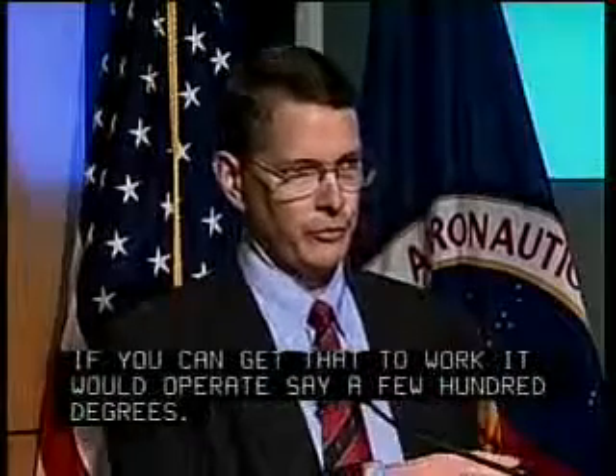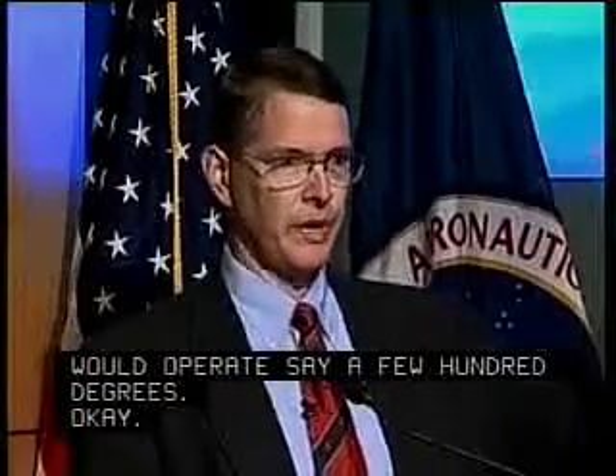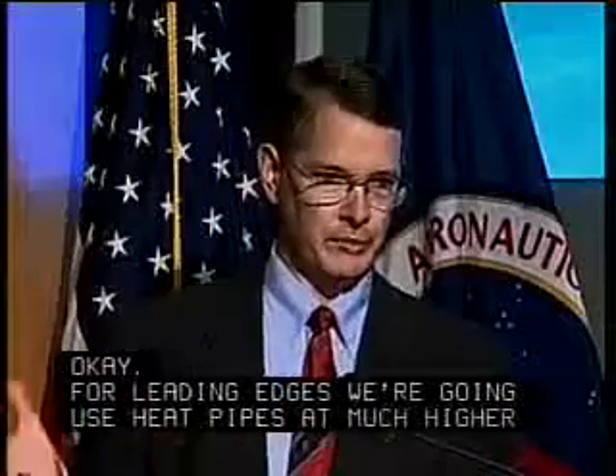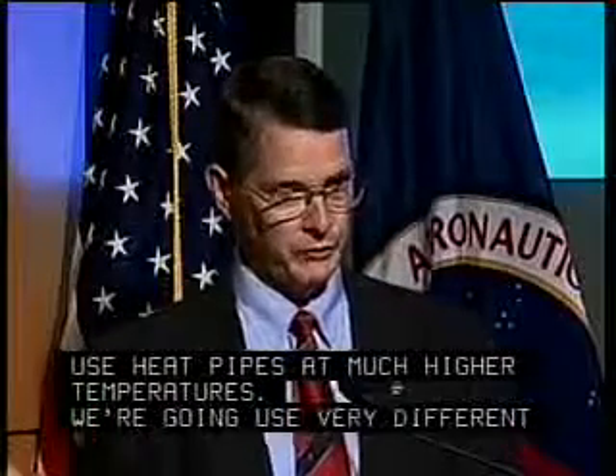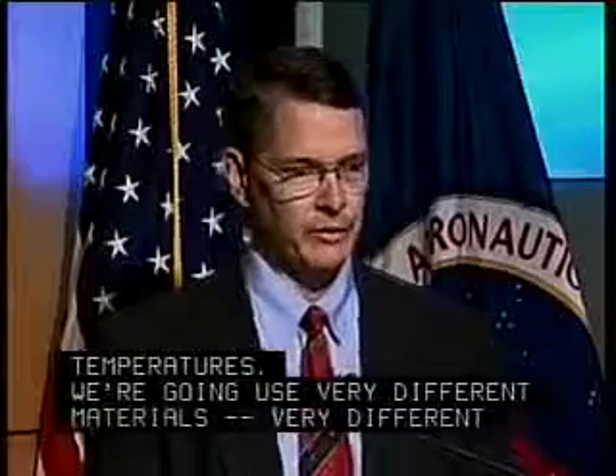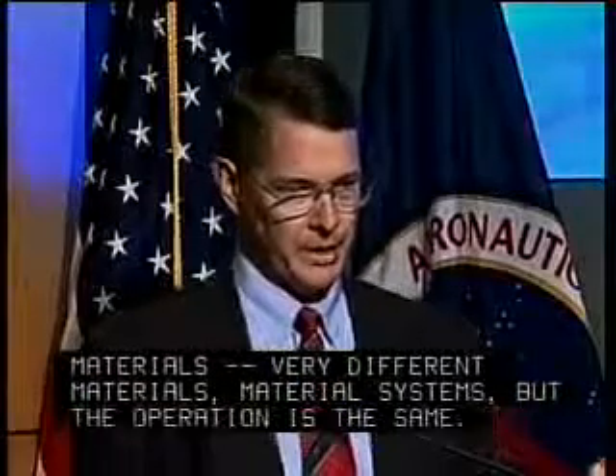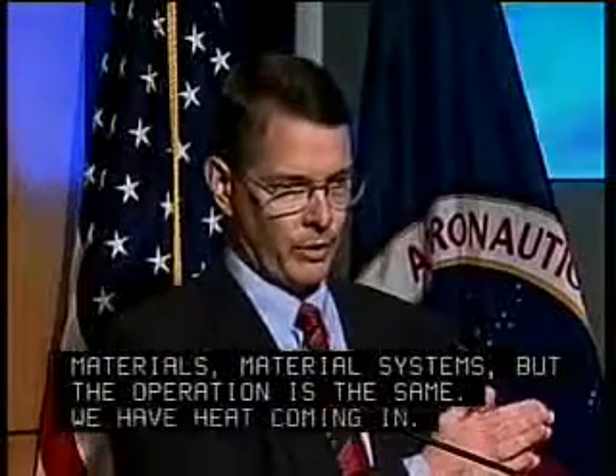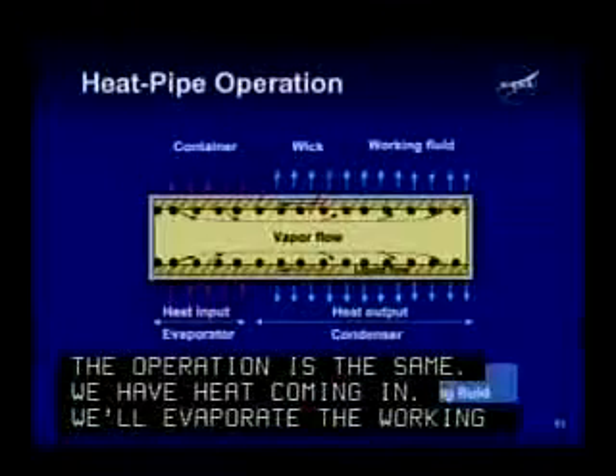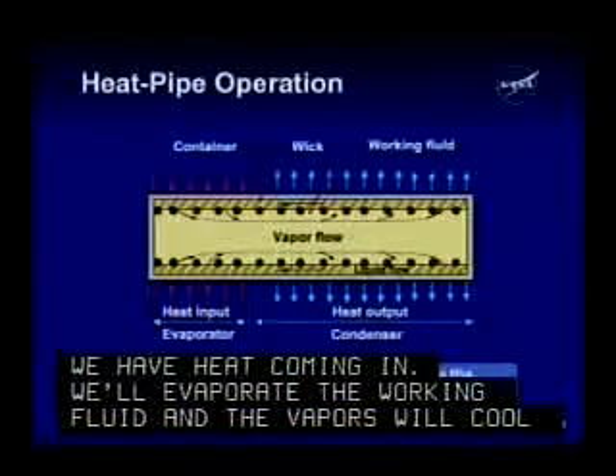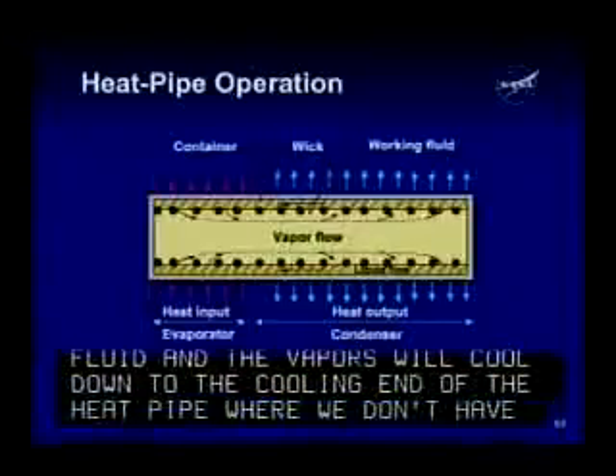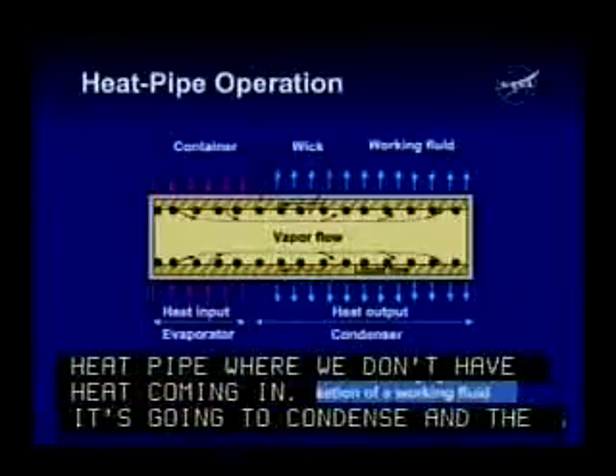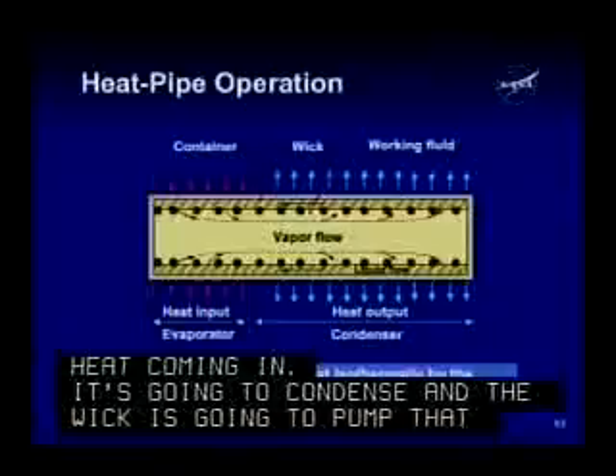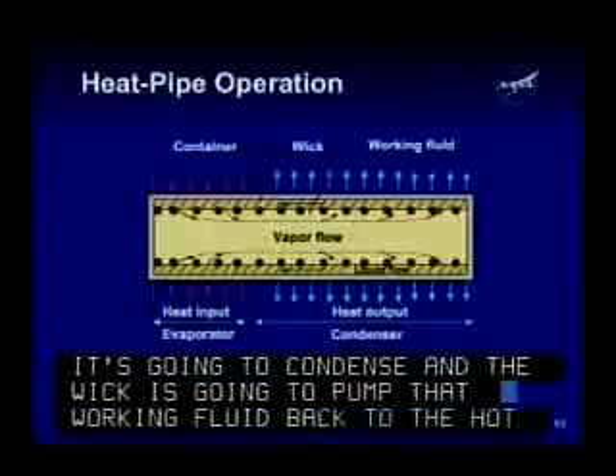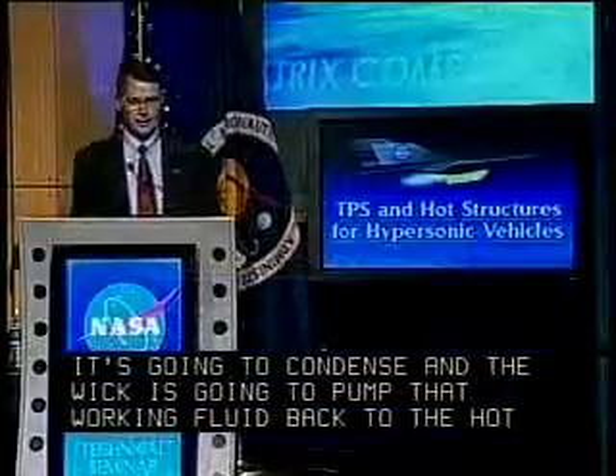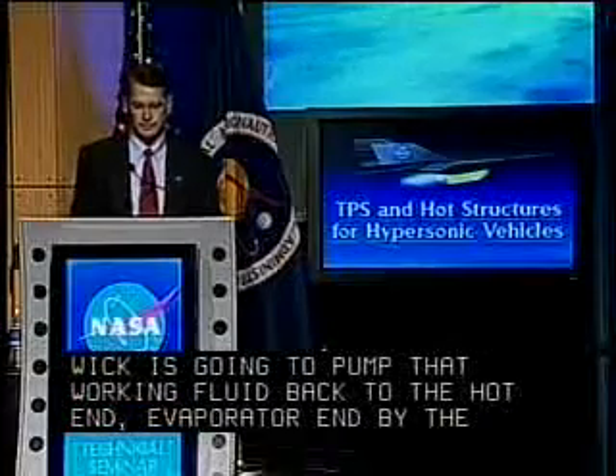For leading edges, we're going to use heat pipes at much higher temperatures. We're going to use very different material systems, but the operation is the same. We have heat coming in, we'll evaporate that working fluid, the vapor is going to flow down to the cooler end of the heat pipe where we don't have heat coming in. It's going to condense, and the wick is going to pump that working fluid back to the hot, evaporator end, by the capillary action of the heat pipe.